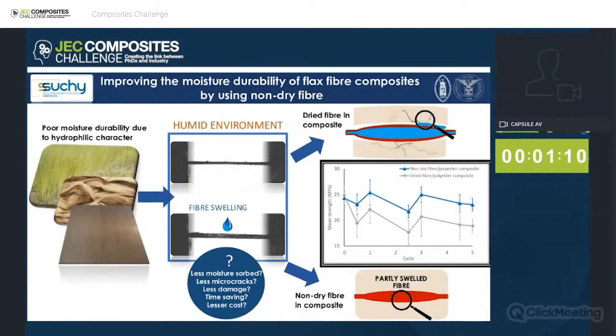So after the durability study, the composites made of non-dry fiber have mean strength of around 18 to 20% higher than composites made of dried fiber. So indeed, the results show that composites made of non-dry fiber and resin with low sensitivity to moisture have lower degree of moisture absorption, lower degree of swelling and shrinking, and the mechanical property is better compared to composites made of dried fiber. Therefore, using this simple approach, not only did we enhance the moisture durability of the composite, we also lessen the time and cost of producing the composite by eliminating the pre-drying of the fibers.